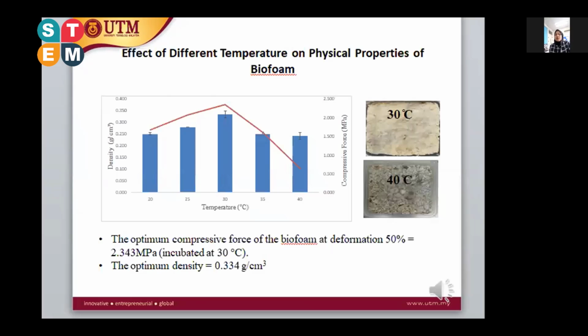Next. So here is the effect of different temperatures on the physical properties of the biofoam. As we can see, density is one of the factors that affect the physical material properties. Low weight and low density of biofoam are favorable properties that we consider in the packaging field. The biofoam grown at 30 degrees has the highest density of 0.334 gram per cm cubed, while 40 degrees has the lowest density, which is 0.242.